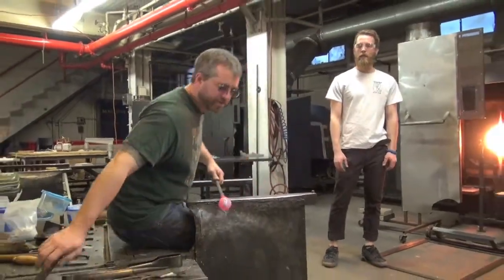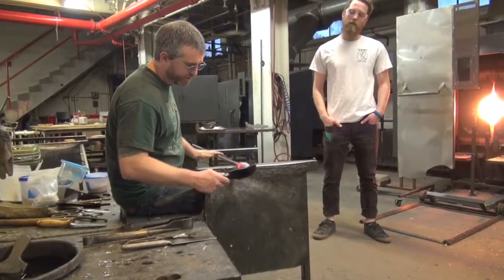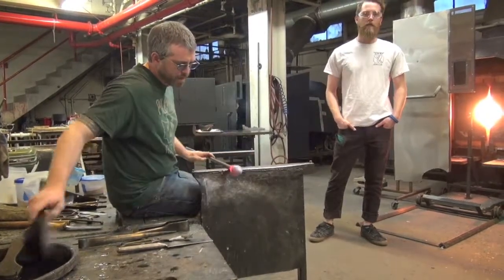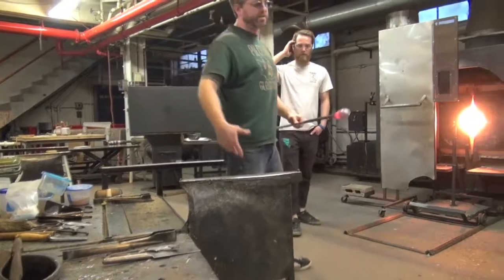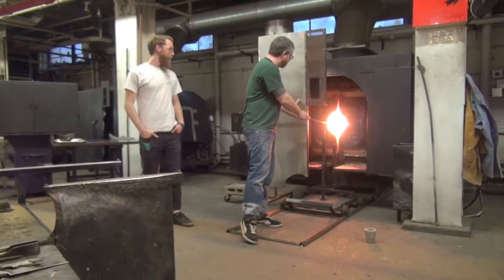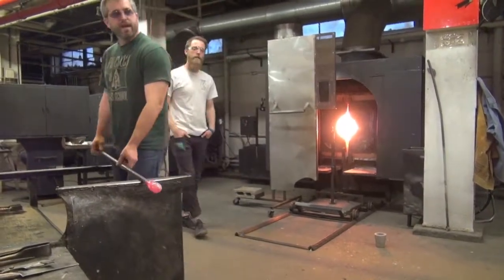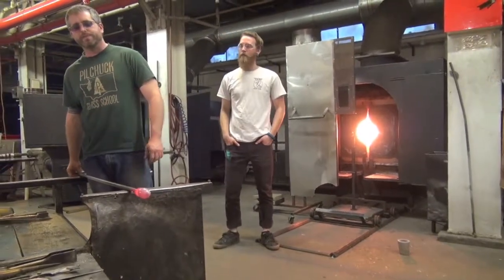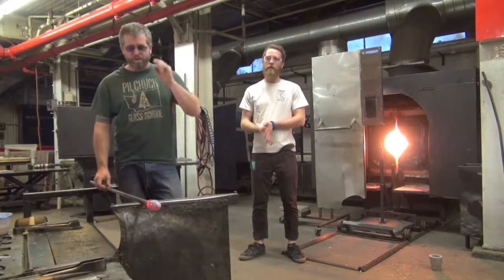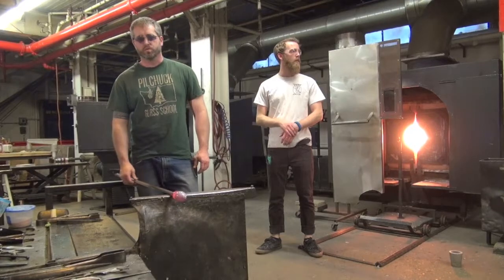The majority of the color I use is actually Gaffer color, which is from New Zealand. And the reason I do it is because all their glass and all their color moves at a very consistent rate. And it just makes things a lot easier, where I can take really, really rich, dense blue, and I can pair that with a dense red, and I don't have an issue where one's going to be really stiff and the other's going to be really fluid. You know, the blue will be more fluid, but it's not such a noticeable difference that it makes it difficult to work with the two.